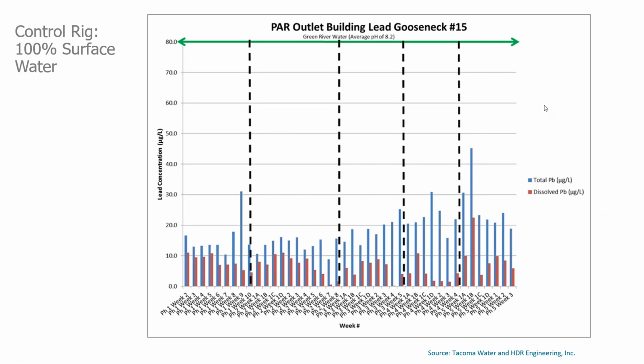This diagram shows the results from the control rig, from one of the goosenecks located at the control station that received surface water the entire time. So these black bars represent phases of changes that occurred at other locations, but not here. So this is surface water the entire time. You can see the red bars are dissolved lead, the blue bars are total lead, so the difference is particulate lead. Generally, we had decent replications across the many weeks, around 9 months of testing, with dissolved lead typically around 10 or under, and then variability in particulate lead. So this is the control.